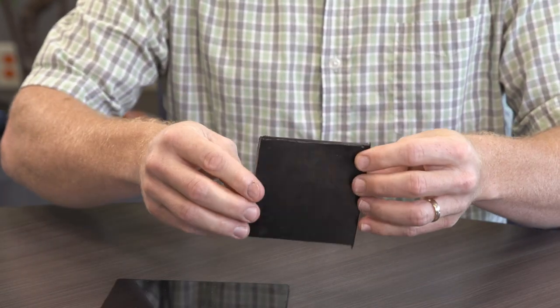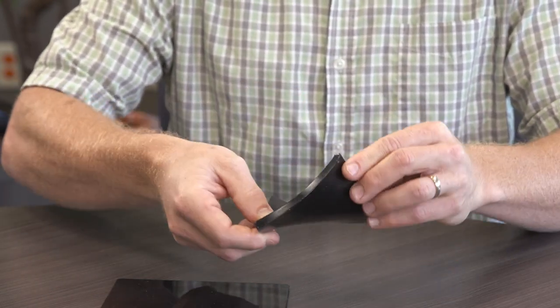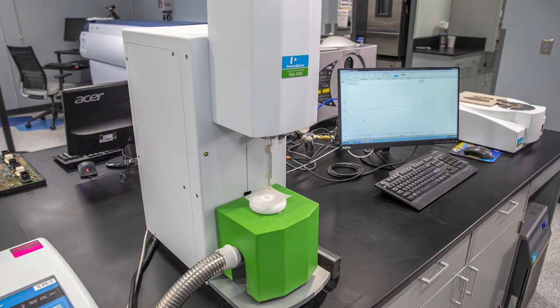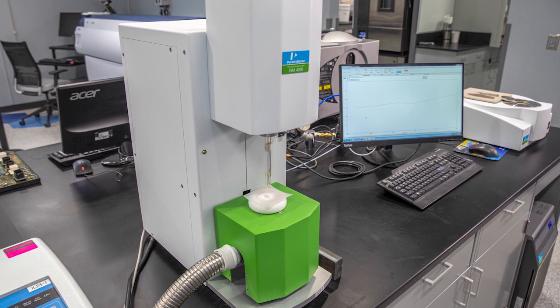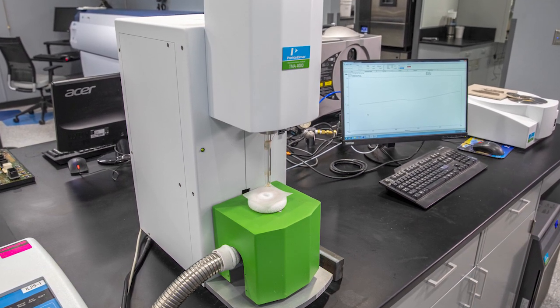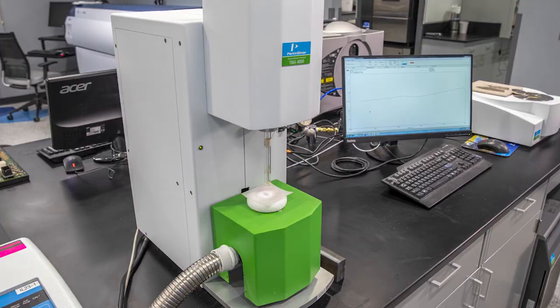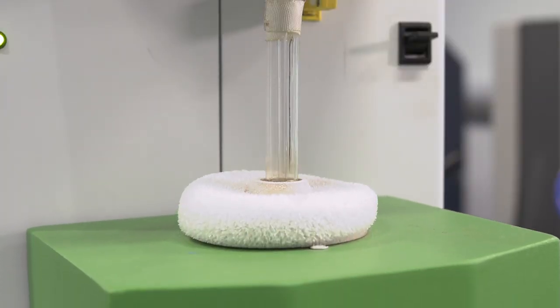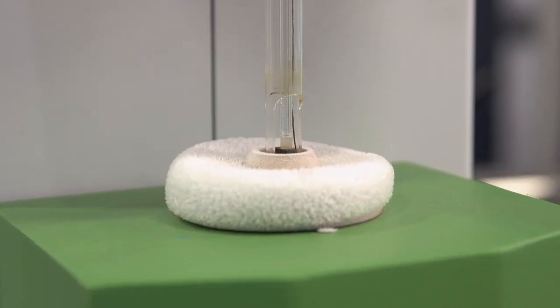To determine how a material responds to thermal cycles, we evaluate the glass transition temperature and coefficient of thermal expansion. The TG is the temperature when a material changes from a rigid glass-type material to a soft, pliable material. The coefficient of thermal expansion, or CTE, is the rate of expansion over a temperature range. We evaluate TG and CTE using a thermal mechanical analyzer, also called a TMA. This measures the height of a sample when ramped through a temperature range.